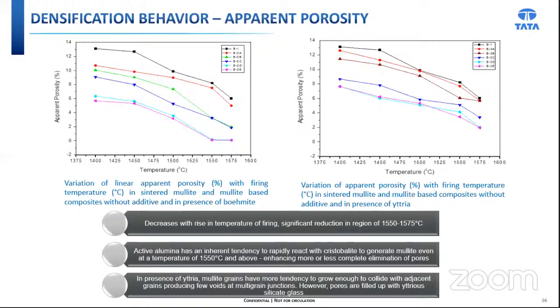However, yttria appears to be less effective than boehmite as an additive in the open pore removal of the sintered mullite body in all additions and irrespective of the firing temperatures.